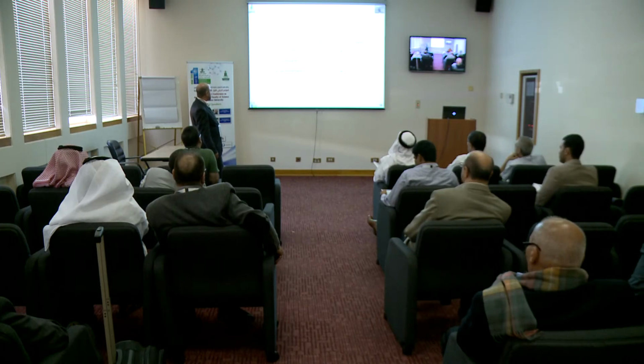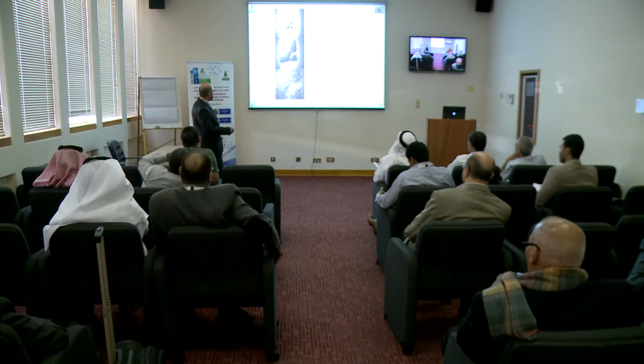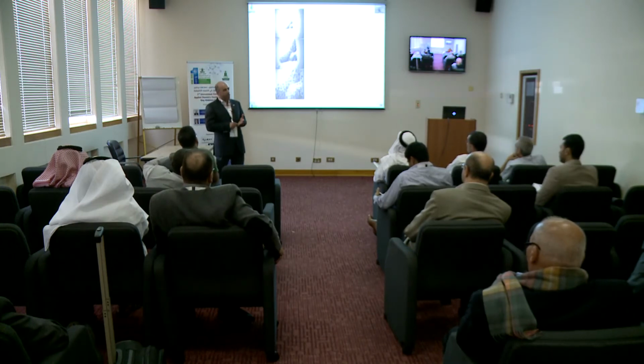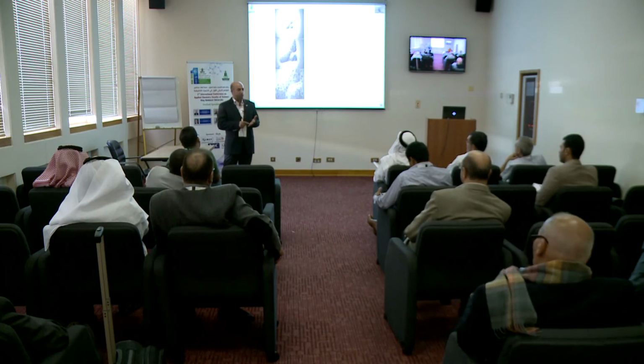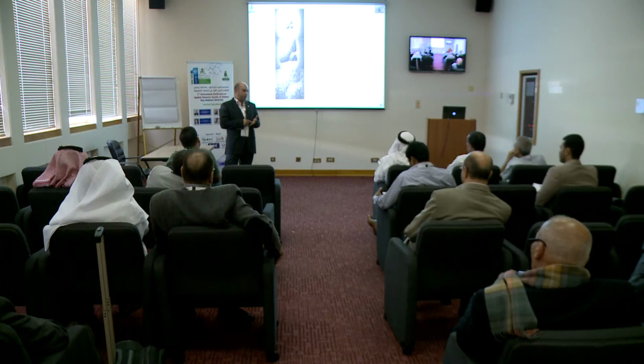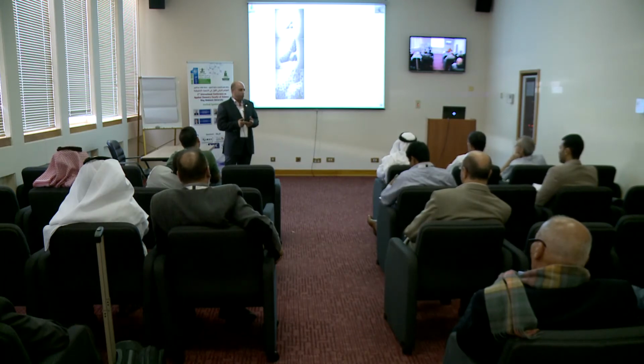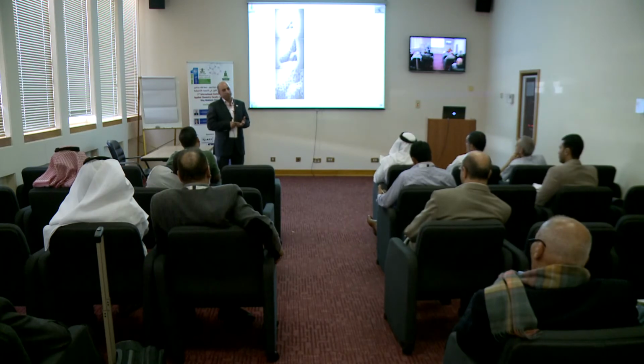One of the problems associated with the zero valence iron nanoparticles, I will just show you, I don't know if it's clear or not. Zero valence iron nanoparticles are very reactive. Once they exist, when we prepare them, they get oxidized by the air or water and change to regular iron oxide. We would like to increase the activity, and at the same time we have to maintain the stability of the iron nanoparticles.